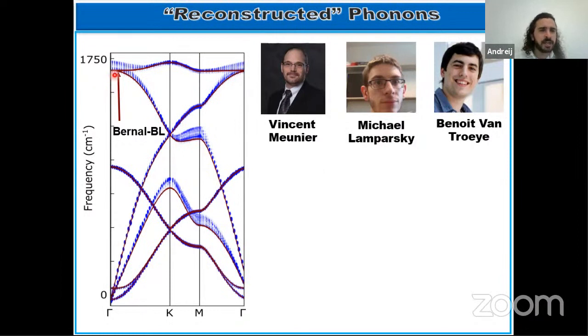And they plotted here in red the dispersion for Bernal bilayer, which is the configuration where the angle between the two graphene layers is 0. And they also evaluated this dispersion for the rTBG of approximately 1 degree. And look, there is a splitting of the phonon branches here and here.